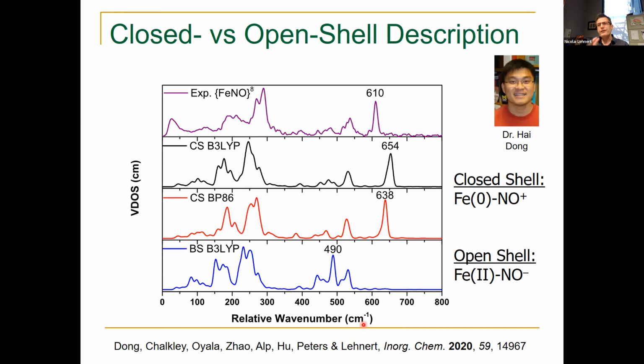The first one was just simply the question, what is the best electronic description of these complexes? Are these closed shell? Are these open shell systems? And here are the experimental NRVS data for the FeNO 8 compound. And this is the iron NO stretch at 610 wave numbers. And then if you perform DFT calculations on closed shell models, which would essentially correspond to something like an iron 0 NO+ type electronic structure, you can see that these calculations here can reproduce the experimental data very, very well.